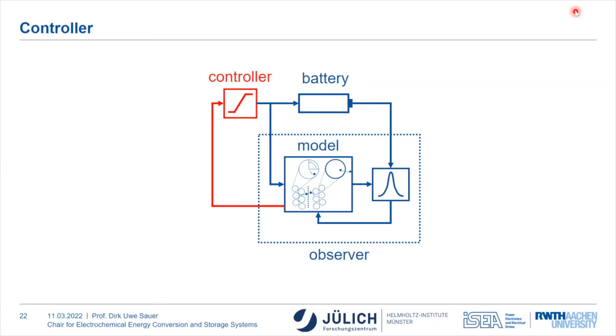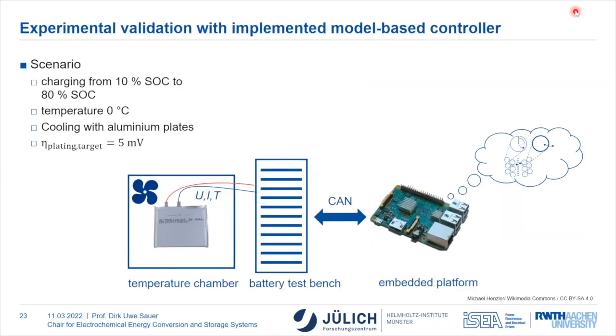And in the example now of charging, the relevant parameter for us from this model is for sure the potential of the anode, of the negative electrode. We all know that the potential for sure has to stay above 0 volts with reference to the lithium-lithium ion reference electrode, because otherwise we get this process of lithium plating, so deposition of metallic lithium, which indeed results in very fast aging. So, and this is what we have done here.